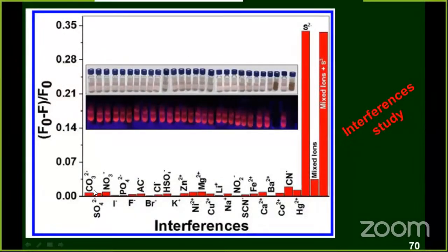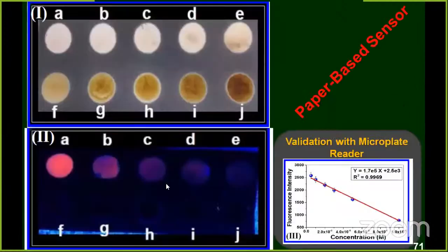Then, very importantly, the interferences in the presence of anions and cations. Interestingly, when we add sulfide, only then is a colorless compound produced. Then all the ions, I added all of them. See here, mixed ions, all the ions. Still it shows the red fluorescence. But when I add cyanide, again the fluorescence decreased.